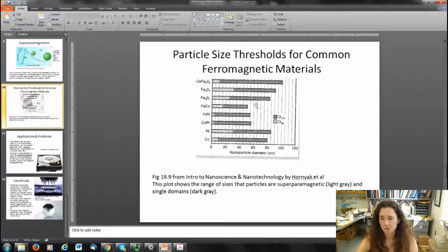single domain particle. Now, as the particle size continues to decrease, there'll eventually be a threshold or critical value of the diameter where it will transition to being a superparamagnet. And that happens in the range of, say, all the way up to 30 nanometers, all the way down to about 10 or 5 nanometers. Okay, that transition happens.